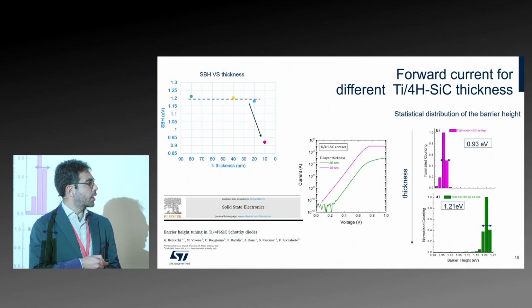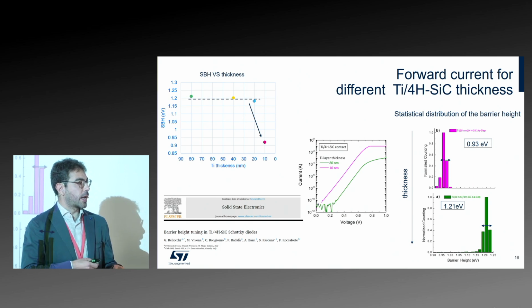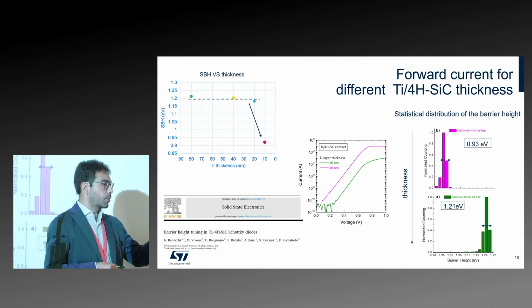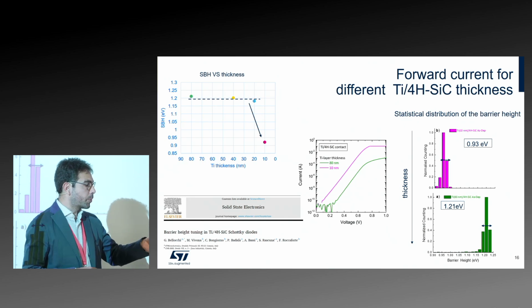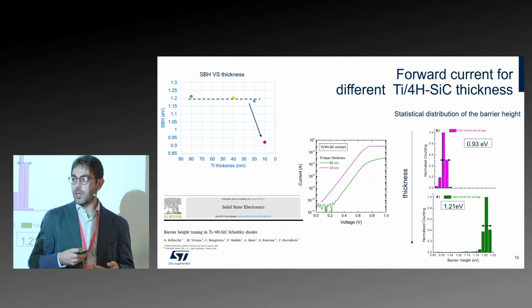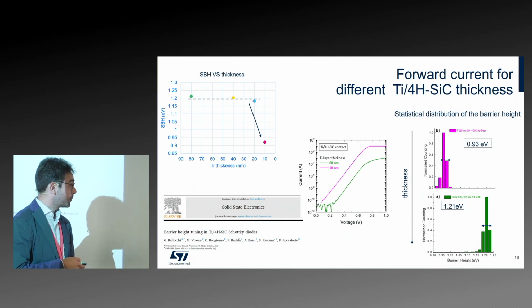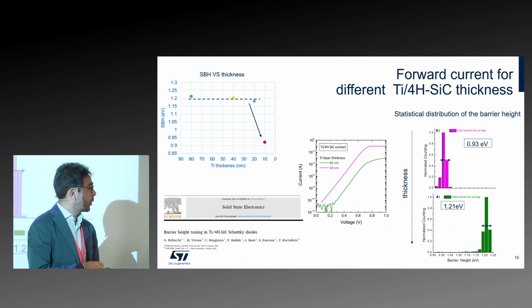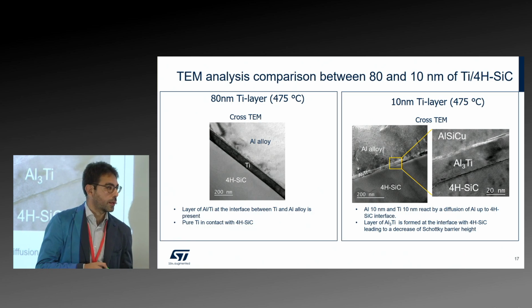And for the titanium 10 nanometers, we got 0.93, as I said before, with the same width. That means that along all my wafer it is very homogeneous. That is a reproducible process that can also be implemented as an industrial one. But we were curious to look at what happened inside my materials.